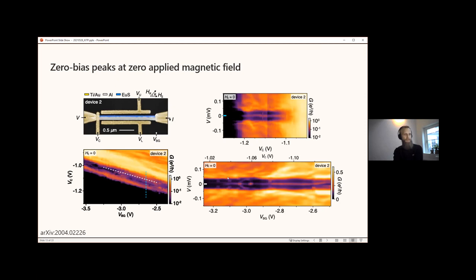You might also notice that there are some sharper resonances here crossing and going through zero, and those you can see visibly here as lines perpendicular to the gate axis, essentially saying that these states mostly depend on the gate, indicating that they live only at the junction. And interestingly, the zero energy state doesn't seem to care too much about these crossings. In any case, to us, it seemed like these states are quite interesting in the context of topological superconductivity, but as Elsa did the nice introduction to it and explanation, I'm going to skip and spare you the details and come to the results that I actually wanted to discuss.